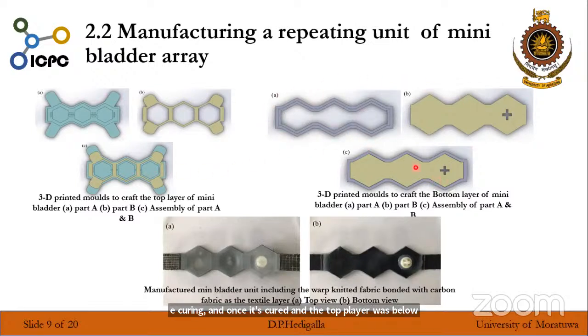Then, in order to produce the entire mini bladder unit, this is the mold number 2 we have used. Part B was inserted in part A, and then, as mentioned previously, the silicone material was poured into the mold halfway, and then the fabric layer was placed onto it, and then again silicone material was poured into the mold such that it completely filled the mold. And once it was halfway cured, the previously manufactured top layer was placed on the top surface of the bottom layer, and then kept for curing. Once the curing is done, the final mini bladder array, as you can see here, was peeled off, and here is the manufactured mini bladder array, top and bottom view.